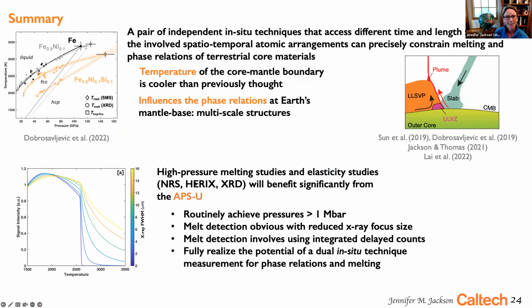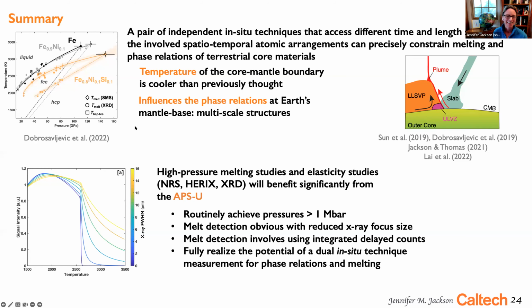Okay, so in conclusion, a pair of independent in situ techniques that access the different time and length scales of the involved spatiotemporal atomic arrangements can precisely constrain melting and the phase relations of terrestrial core materials. In particular, we studied iron-nickel-silicon alloy, showing that temperatures of the core could be reduced such that the temperature at the core mantle boundary could be about 3,500 Kelvin. This would influence the phase relations at Earth's mantle base, which also influences the dynamics of this region.